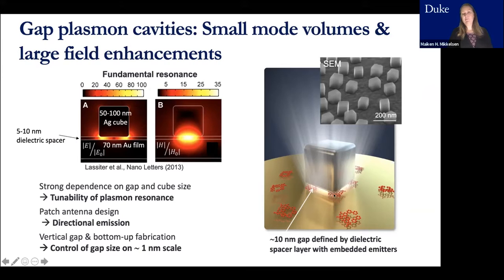And we can embed emitters directly in this gap. You can see we have the highest field enhancement in the gap region underneath the cube here, and the field enhancements can get up to 100-fold. You can see we have both electric and magnetic field enhancements. And this is SEM, so you can see these are indeed small cubes. These are colloidally synthesized and single crystalline, but you can also fabricate simpler structures by using electron beam lithography on top. I mentioned electron beam lithography is not always giving us good enough resolution for the critical dimension, which is the gap here, but for the dimensions of the nanoparticles on top there are less stringent requirements. This structure has a strong dependence on both the gap size and the cube size, which means that we have two knobs to control the plasmon resonance. They also have a nice directional emission, so if you have emitters coupled underneath, they will emit to the far field.